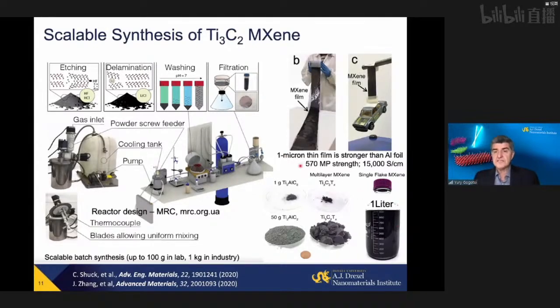And what is also nice, you can process it from an aqueous slurry. MXenes have oxygen or OH groups on the surface, so they are hydrophilic and negatively charged. You can concentrate, make, for example, a liquid crystalline solution and use the Dr. Blade method to produce this film. It's just 1 micron thick and it has strength higher than aluminum foil and about 15,000 Siemens per centimeter. No additive, nothing. You just spread the solution with a Dr. Blade, dry it, and you get this film. Considered as an electrode current collector.